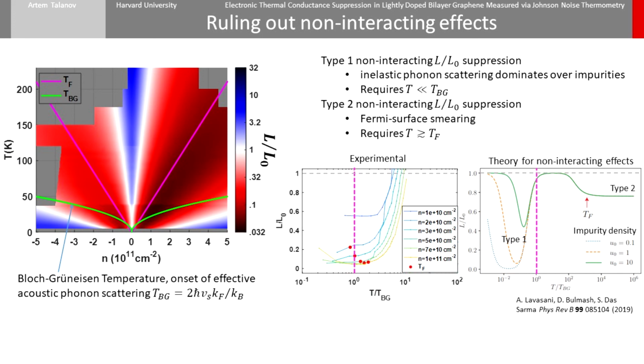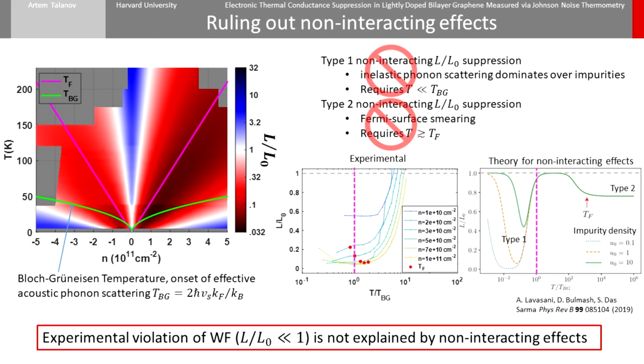Our experimental data in a corresponding plot looks like this. The suppression begins far above the Bloch-Grüneisen temperature, so we cannot attribute it to inelastic phonon scattering. The second type of suppression, caused by thermal smearing of the Fermi surface, occurs at temperatures above the Fermi temperature. The Lorentz ratio is 1 below this temperature and decreases to a constant value above it. This does not match our experimental suppression, so that cannot explain it either.